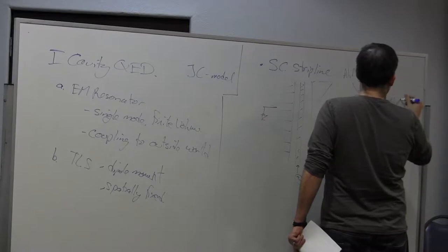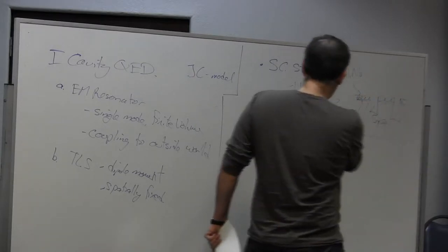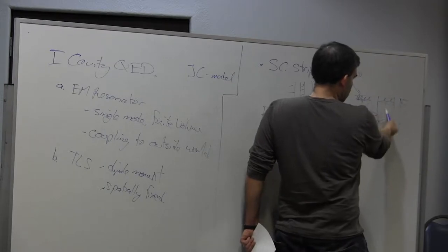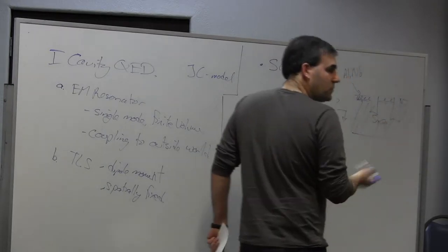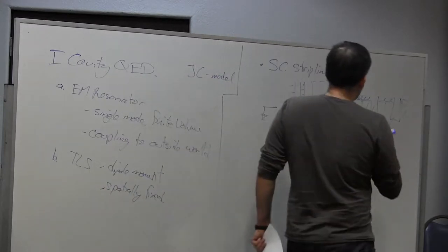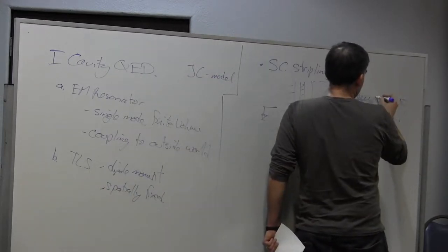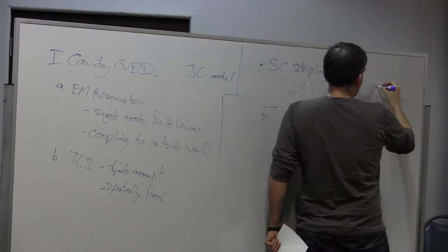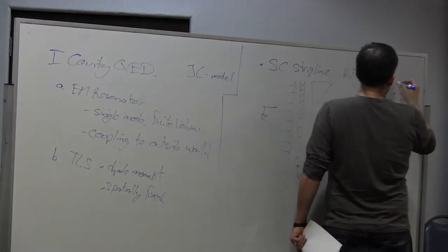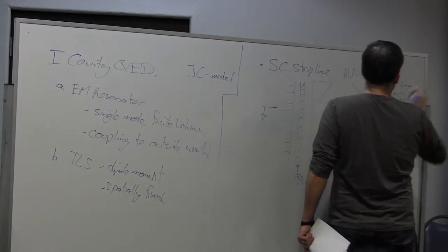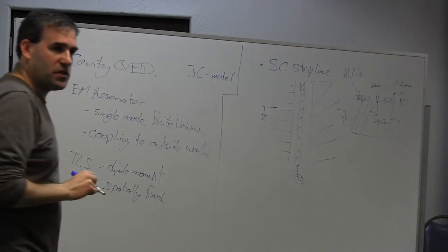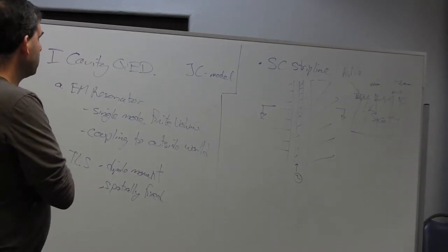That's it. Okay, so this would be a side view, where this is the top view, and you have this superconducting strip which is connected to an insulator, but that's the way in which it's suspended. And the dimensions here are that these thicknesses are submicron, maybe 200 nanometers or so, and all these other dimensions are in the 1 to 5 micron range or so. So they're fairly standard objects to fabricate.